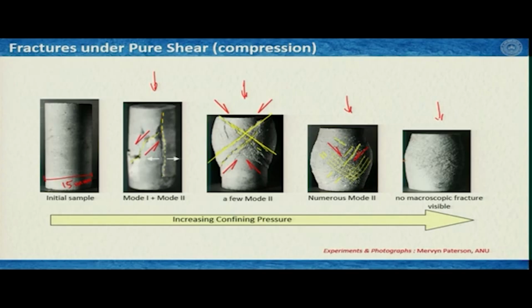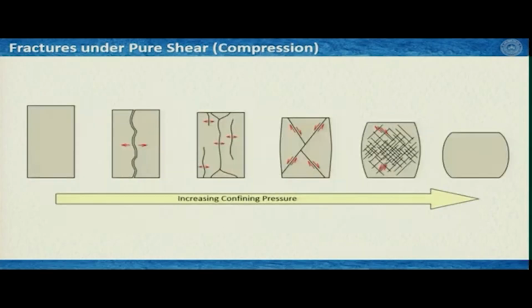When you go to a higher confining pressure, the highest in this range of experiments, you hardly see any macroscopic fracture. However, a very close look would give you an impression of a series of very tiny small scale fractures in the sample. So, there is a transition in the fracture patterns with the confinement of the sample, and if we try to summarize it in a different way by sketches, we can figure out that when the confining pressure is low or there is no confinement, then the rocks would produce mostly tensile fractures, as we have seen here.